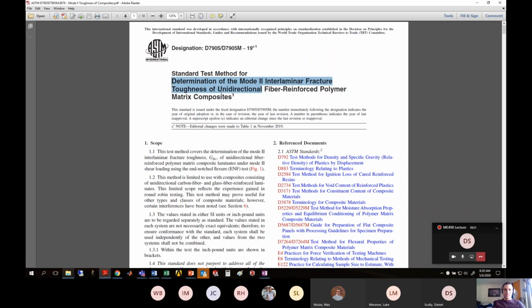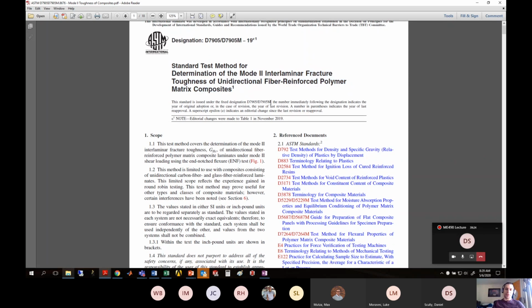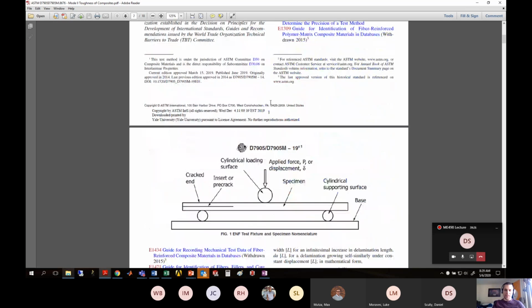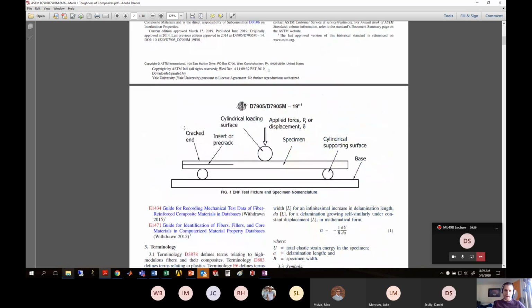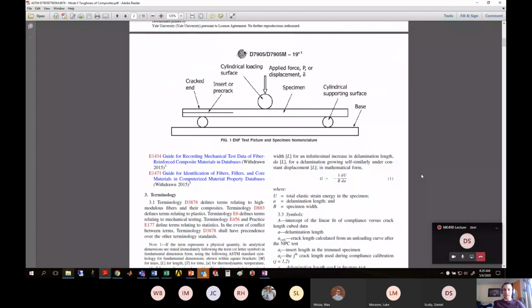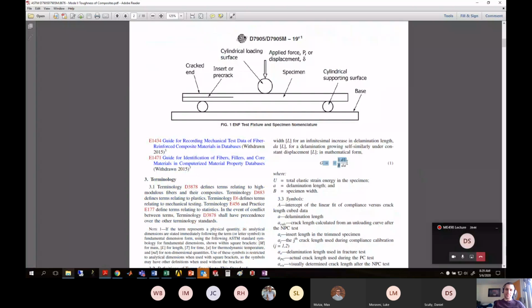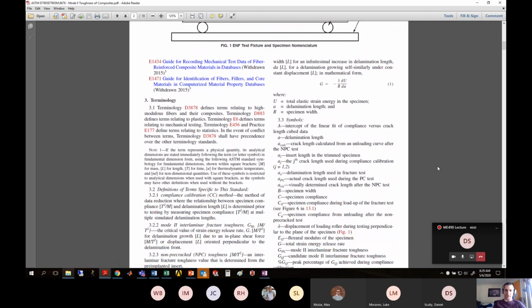Mode 2 interlaminar fracture toughness of unidirectional fiber reinforced polymer matrix composites. All the information is here, and this is our sample geometry. We've got a cracked end, the pre-crack, on the left-hand side. This is for end notch flexure, ENF, test fixture and specimen nomenclature. It describes everything associated. Here again, it's indicating that the critical strain energy release rate, G, is 1 divided by the sample thickness, 1 over B, times dU/dA, the amount of energy required to propagate the crack a certain amount. Same stuff we've been talking about: dU is the change in energy, dA is the change in crack length. This is exactly what we've been talking about so far.